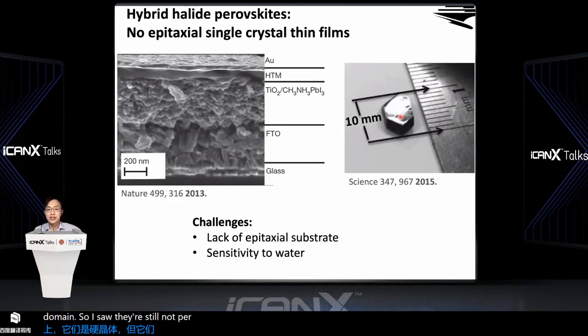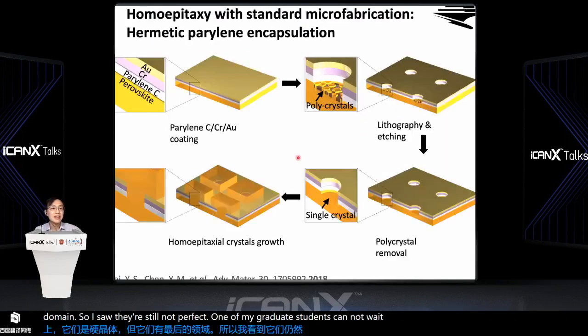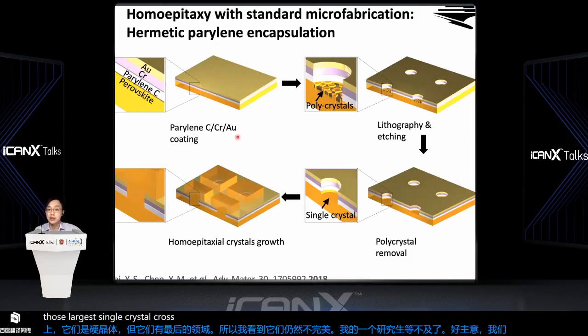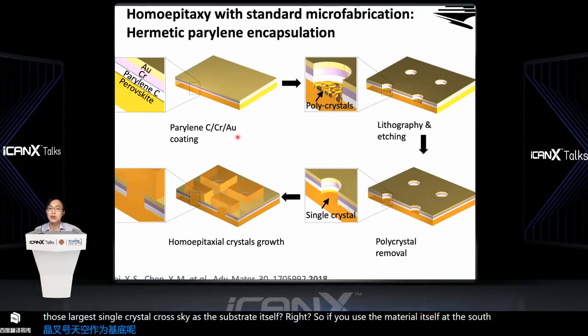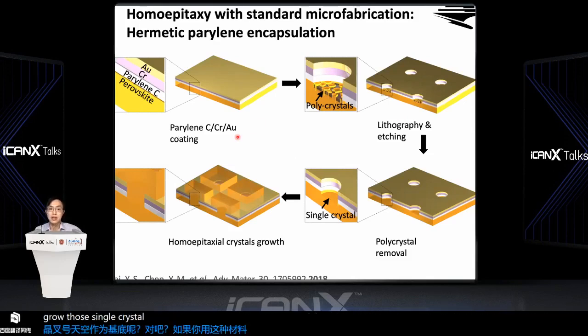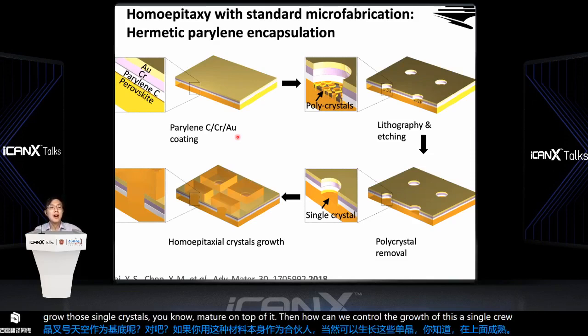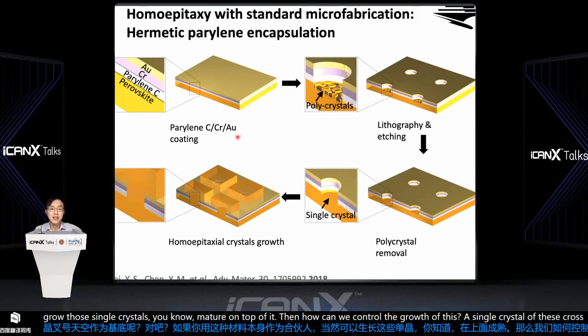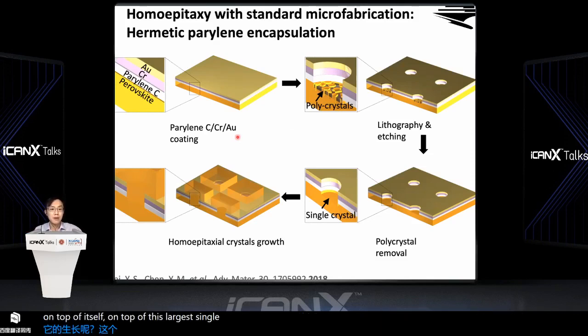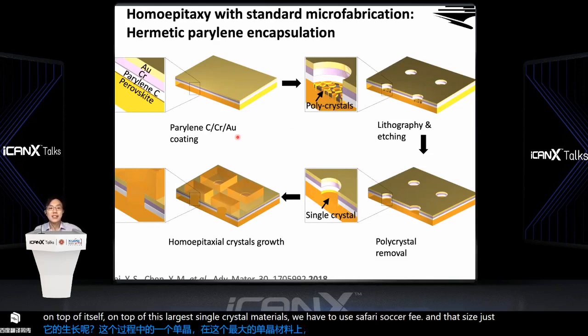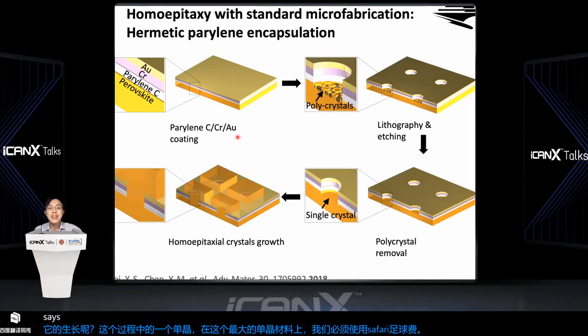Then one of my graduate students came up with this fantastic idea, saying, why don't we use the large single crystal perovskite as the substrate itself, right? If you use the material itself as a substrate, then of course you can grow those single crystal materials on top of it. Then how can we control the growth of this single crystal thin film of this perovskite on top of this large single crystal bulk material? We have to use photolithography. And as I just said, this material is very sensitive to water. How can we prevent this material from decomposition, right?